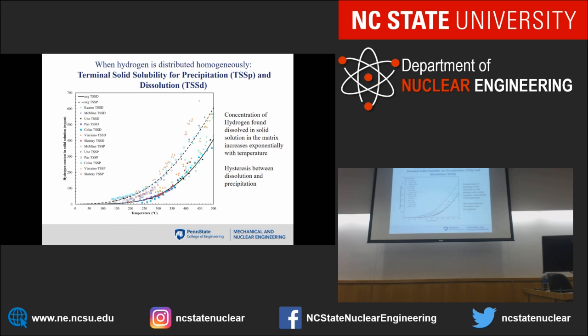This is shown here, but just look at the solid curve. What that means is that if I have a hydrogen content of 100 ppm, I'm going to be precipitated at room temperature. I get to the solid curve, the hydrides are dissolved. Above here, everything is in solid solution. Now let's say that I'm doing the opposite. I'm coming from high temperature and cooling down the same sample with 100 ppm. I'm only going to precipitate at the dotted line.